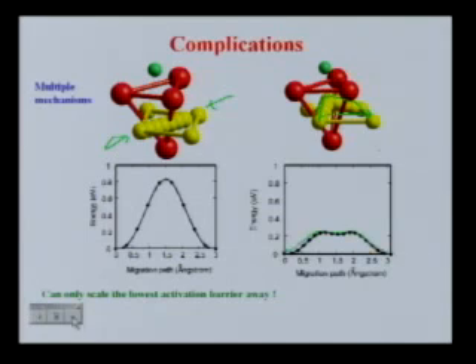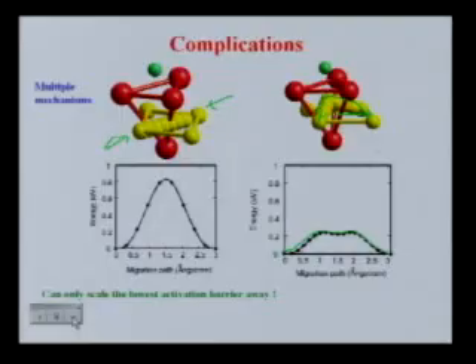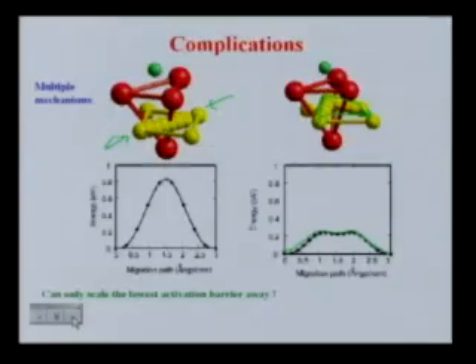And that's actually a path that, if you do elastic band, is so much lower—only about 200 millielectron volts. It shows the real problem you can run into: when you do kinetic Monte Carlo, you have to assume what your paths are for transitions, and if you don't get them right, you can be seriously wrong. That's one of the nice things about MD, that it's unbiased, so it would find these things for you. But these are actually the only two paths, and because the activation barrier of this one is so much lower, this is pretty much the one that gets executed almost all the time.